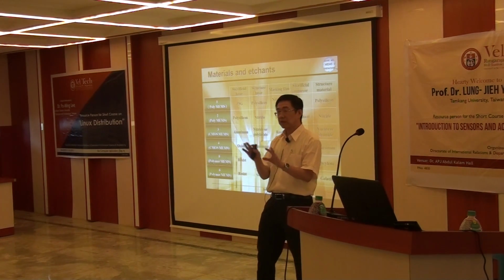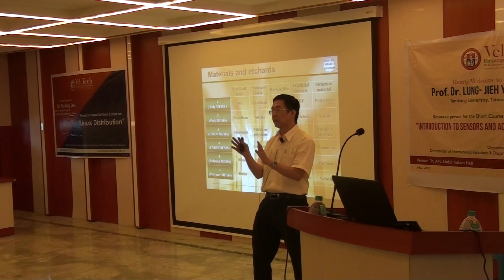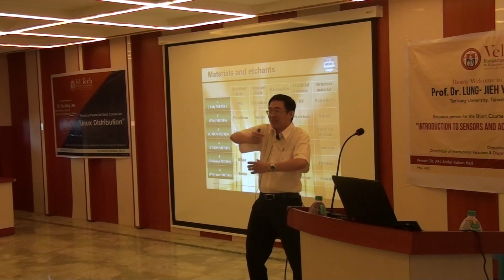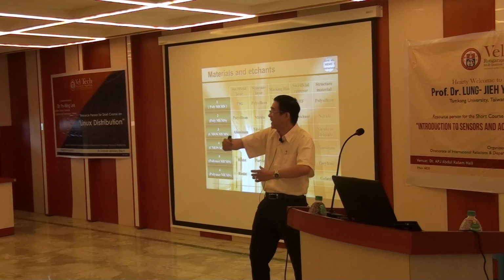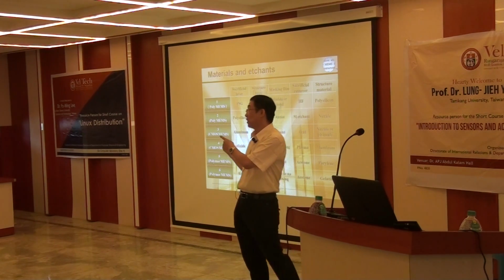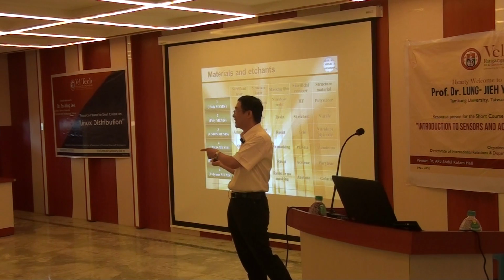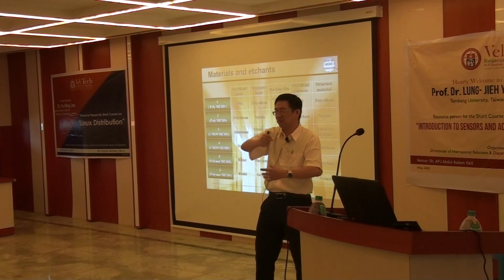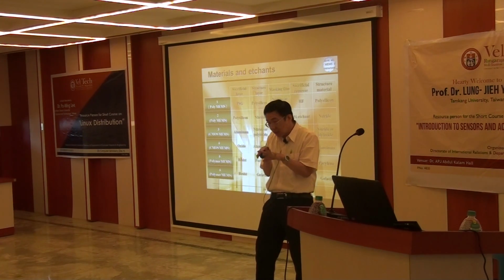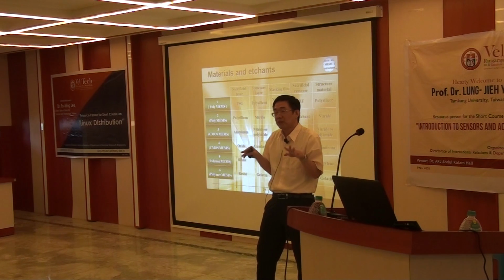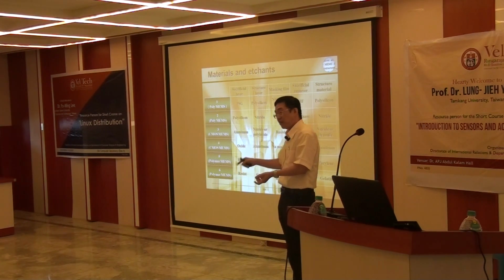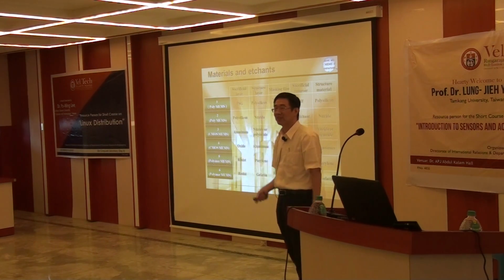Second, if you use gelatin, it's similar. We know how to process gelatin and photoresist. You can try to cook it now. You can buy gelatin powder from the market, and then you can do the cooking, at 40 to 50 degrees C, into a gel-like liquid. And we do the process, spin coating, like the photoresist.